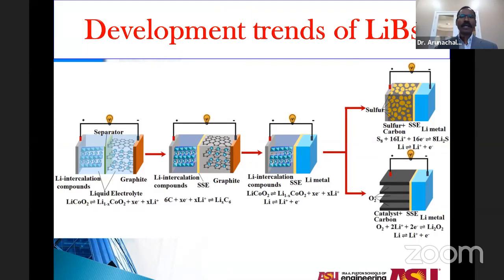So this slide gives you an idea about where the market is going. You can see at the left end the currently available lithium-ion batteries with a liquid electrolyte. You can also see a separator. Again, the anode is on the right-hand side with the graphite, and on the left-hand side is the cathode, which allows the intercalation of lithium back and forth during charging and discharge. If the separator and liquid electrolyte are replaced by a solid-state electrolyte, then there's no separate membrane or separator, but just a single sheet. That could physically separate and also ionically conduct lithium between anode and cathode during charging and discharging. And the bulky graphite electrode can be replaced by lithium metal if you optimize the solid-state electrolyte. That would again certainly improve the energy density.